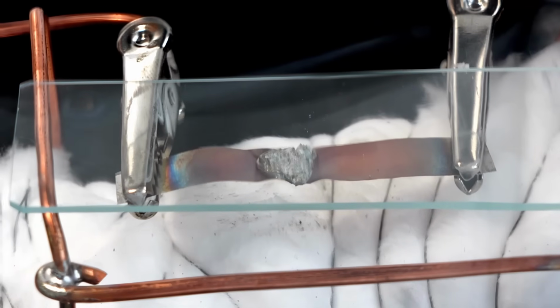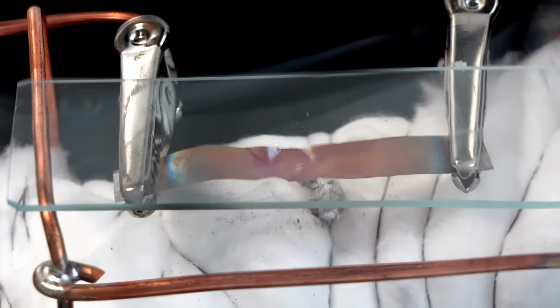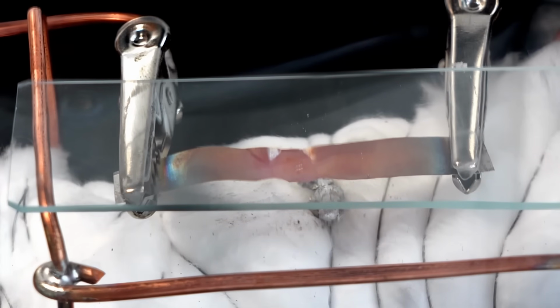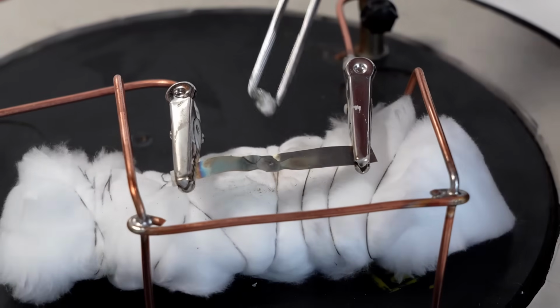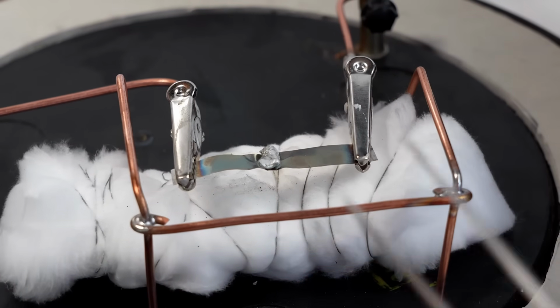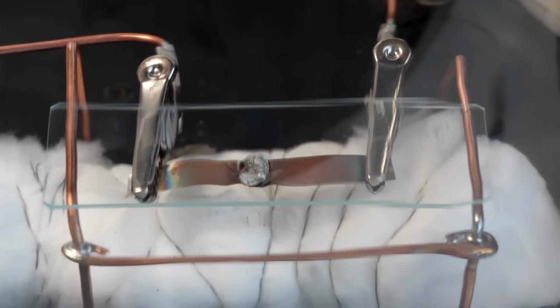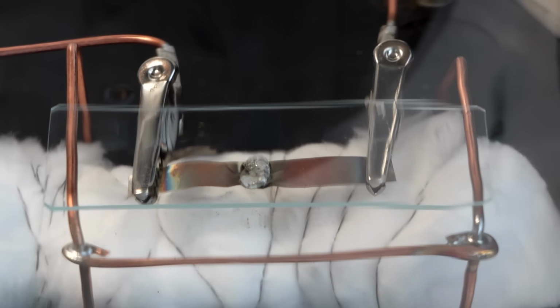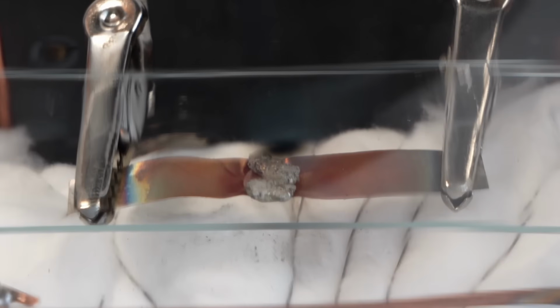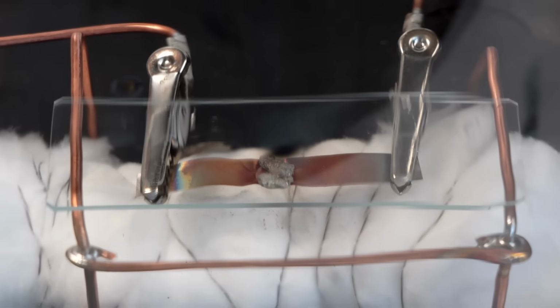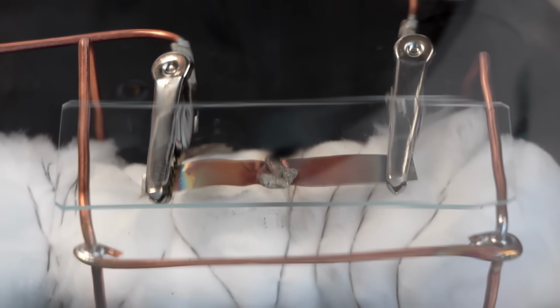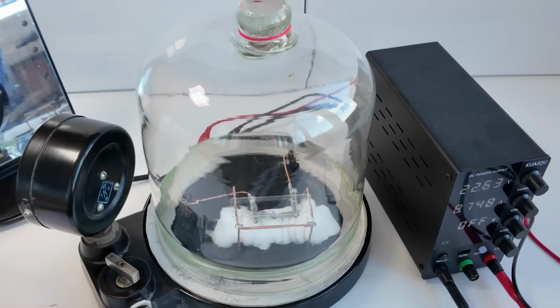It turned out that the boiling started very abruptly, causing the molten piece of zinc to even fly off the heating strip. I had to stop the experiment and put this runaway piece of metal back in place. After reheating the metal a second time, all that was left was to wait for it to boil. Did you see that? Exactly the moment when the zinc boiled, and vapor settled on the glass. And there it goes a second time. Yeah, definitely didn't look the way I expected. And the metal vapor itself was almost invisible here, except for the metal that settled on the glass surface.